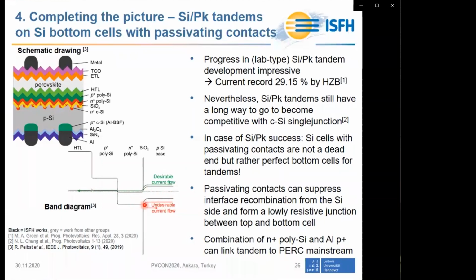And this could be achieved either by a passivating contact, for example, formed with a silicon heterojunction, or by a passivating contact formed by a polysilicon and oxide junction. And in the case of the latter, the temperature stability of the junction scheme allows you, for the processing of the bottom cell, to also apply the current metallization of the rear side, which links the tandem concept to the current PERC mainstream cell technology.